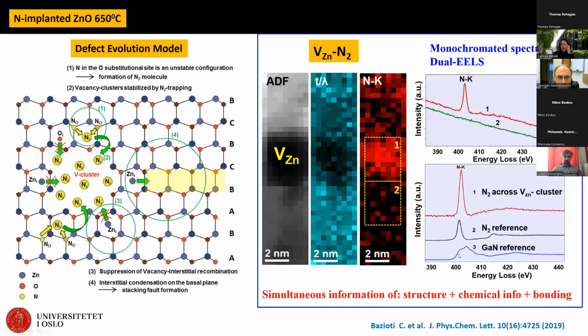For the gallium nitride bonding, I had a pure gallium nitride sample. And of course, with respect to the bonding of nitrogen with zinc, we were asking to have a zinc nitride sample, but we were informed that it is an extremely thermodynamically unstable compound, and it's very hard for people to grow zinc nitride. And this, of course, is already an explanation of the phenomenon that we see. Nitrogen doesn't want to bond with zinc.